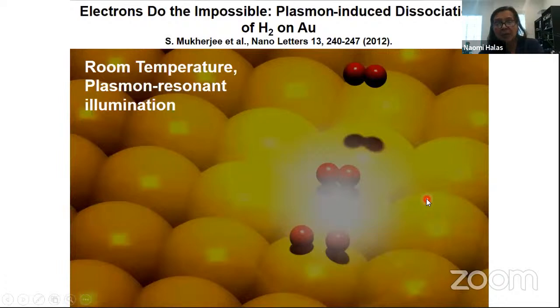This is the first reaction we ever did in this context. I like to refer to it as the simplest reaction that we can think of. It has no side reactions, where we have H2 molecules interacting very, very weakly with the gold surface. These are small gold nanoparticles. We flow the H2 over the surface. We also flow D2 over the surface, okay? And what we want to do is dissociate the H2. Normally that's a high temperature process. It's a significant barrier, but we're going to do it at room temperature.